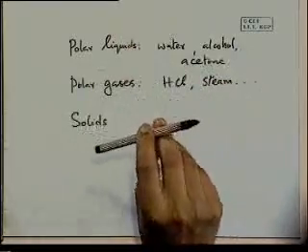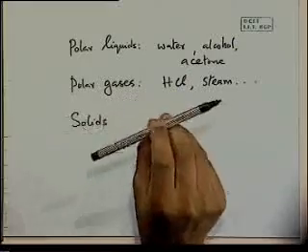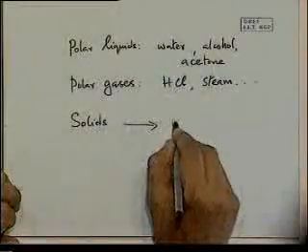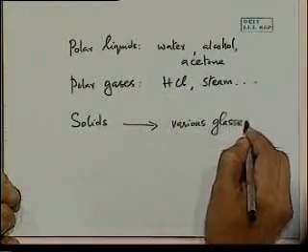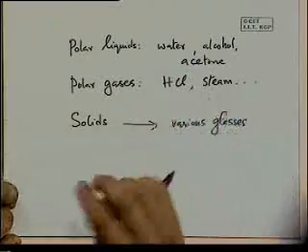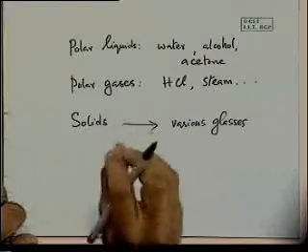Remember, here it is something that is going to rotate. And in a solid, it is going to be very difficult for the parts of it to rotate because they are all rigidly held together within a structure. Nevertheless, it is seen in certain types of glasses where the structure is more open. It's an amorphous kind of structure. And it's strictly not simply a rotation. It may actually involve an ion jumping from one side to the other side.